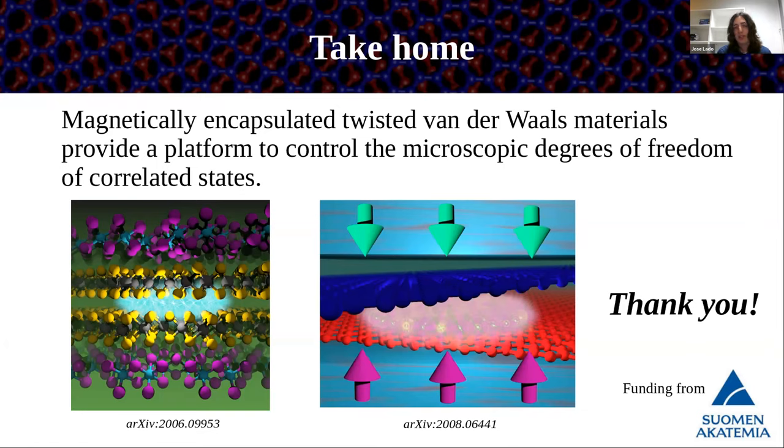In the case of twisted dichalcogenides, apart from that, one also gets some strong relaxations of the structure. But it turns out that the magic angles appear in similar ranges. The only difference is that for twisted dichalcogenides, one gets a continuum of magic angles. So once you go below a certain threshold, your bands are pretty flat most of the time. Whereas in twisted bilayer graphene, you get some very specific angles at which they are the flattest. So I'd say that there's not an easy answer of why they happen at similar angles. But you can think that generically, when you have twisted materials at relatively small angles, you are always going to get flat bands.